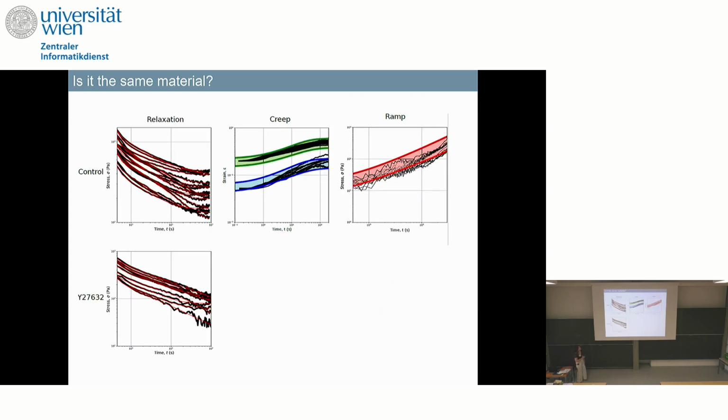So this is the control scenario. So we also predicted the ramp up to 30% deformation because then it becomes highly nonlinear. So this is the prediction of the ramp response using the same parameters that we obtained from the fit of the relaxation. And then we did treat the samples pharmacologically to alter the cell contractility. So the cells do contract. So we removed the cell contractility. We fitted the relaxation response. And we can see that there,